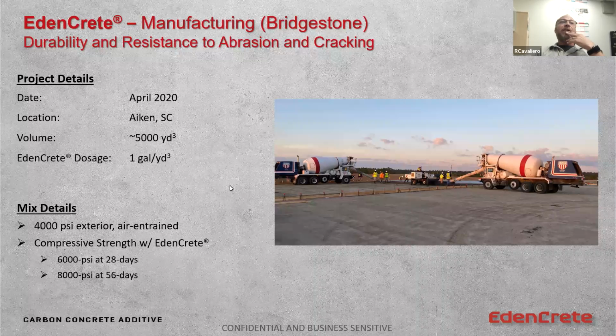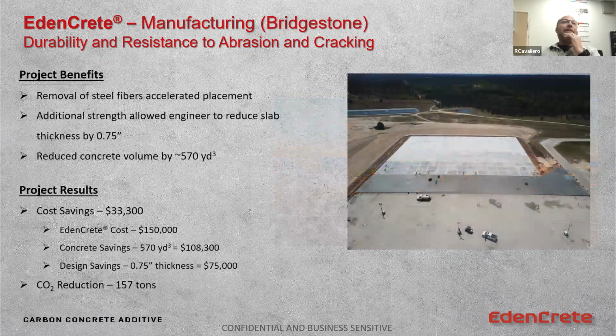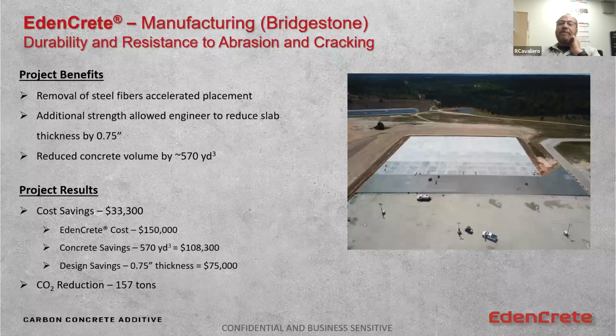So we put EdenCrete into a design that was 4,000 PSI, and the mix hit 6,000 PSI at 28 days, and it hit 8,000 at 56 days. We worked with the engineer at Cranston Associates, and we used that to optimize the design. We reduced the thickness of a 10-inch thick slab by 3/4 of an inch. The slab totaled 165,000 square feet, so saving that 3/4 of an inch saved 570 cubic yards of concrete. We ultimately saved $33,000, all in.